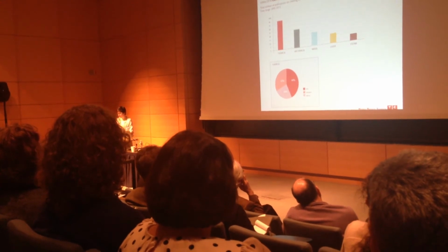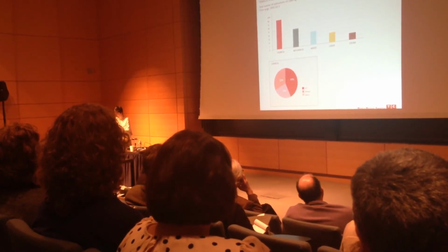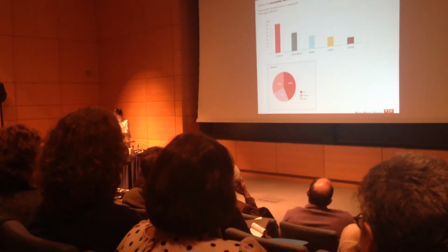Still remaining to look at the cleaning methods, as we mentioned, chemical has been the most popular, also comparing to the different data. And between chemicals, we have acid, which leads with 44%, then alkaline with 24%, which is often used in combination with acid as a pre-wash alkaline and then a neutralized acidic afterwash. And then finally, we reach detergents, which represent 32%.